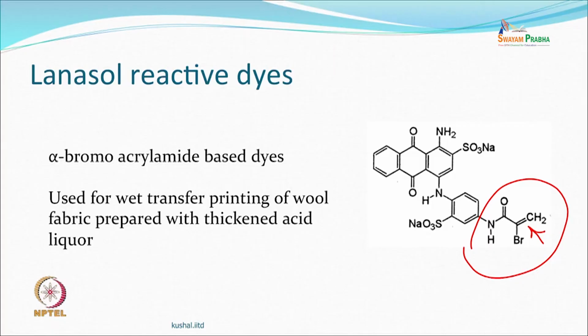This treatment is just, I'll give you the next one. So this is a reactive dye. So you have basically an alkali and some viscosity modifier, so that the spread doesn't take place so much. Like when you have a tailing effect in a dyeing padding system, you add sodium alginate and some such high molecular weight compound, so that the tailing is reduced. So here also a bit of a viscosity modifier, but still it is a padding process and not a paste process, and that's the kind of thing basically.